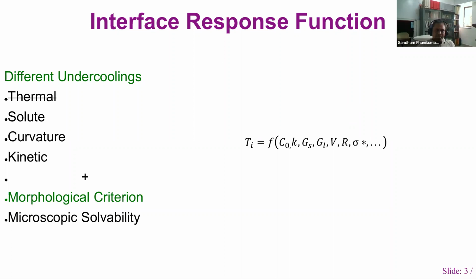But I want to tell you that the metallurgical knowledge of the interface temperature during solidification, as a function of the initial composition, the partition coefficient, the gradient of temperature in the solid, the gradient of temperature in the liquid, the velocity of the interface, the radius of the dendrite tip, and so on, can all be modeled today through analytical modeling. The only difference between casting and additive manufacturing is that in additive manufacturing, you always have a build plate. So there is always an initial solid which is growing into the liquid pool, and therefore the thermal undercooling can be neglected. That's the one difference with the model, but the remaining things are all applicable, and therefore one can use the casting or welding literature and apply it to additive manufacturing.